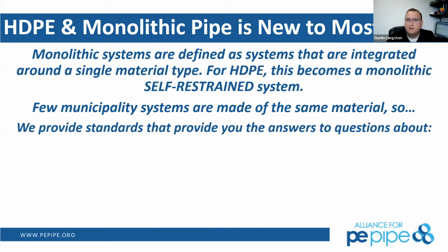So HDPE pipe, we really didn't see that. It's a monolithic pipe system, and those are fully restrained, self-restrained fusion joints. So one of the other system failures you find with PVC and ductile iron is if you don't thrust block them correctly, you're going to have gasketed fittings push off at the end of the pipe, whether it's a T or an elbow. So HDPE pipe, again, is fully self-restrained. You weld it together and it's not going to come apart. And there's no need for thrust blocking unless you're transitioning to another pipe material.